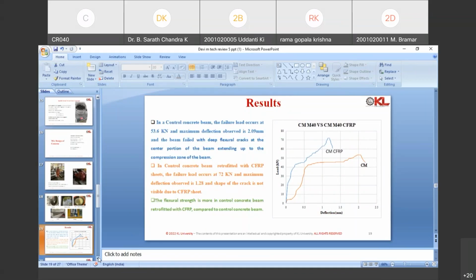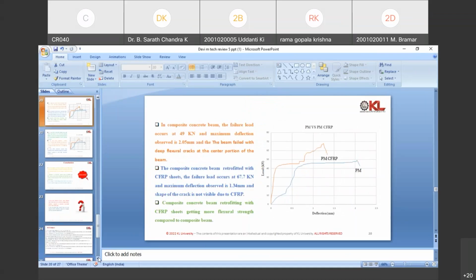In the control concrete beam retrofitted with CFRP sheet, the failure load occurs at 72 kilonewtons and maximum deflection observed is 1.28 mm, and the shape of the crack is not visible due to the CFRP sheet. The flexural strength is more in the control concrete beam retrofitted with CFRP compared to the control concrete beam. In the composite concrete beam, the failure load occurs at 49 kilonewtons and maximum deflection observed is 2.05 mm, and the beam failed with a deep crack at the center position of the beam. With the composite concrete beam with CFRP sheet, the failure load occurs at 67.7 kilonewtons and the deflection observed is 1.36 mm. The crack shape is not visible due to the CFRP sheet covering the beam. The composite concrete beam retrofitted with CFRP sheet has more flexural strength compared to the composite beam.